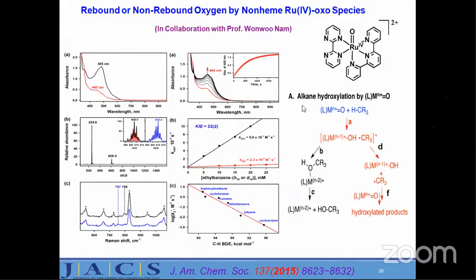So what is a rebound mechanism? If you look at this particular mechanism here, you have a metal oxygen species. The hydrogen is abstracted, and it remains here. You have a radical, and then you have OH. Once hydrogen is abstracted, the hydrogen goes with the oxygen, so it becomes manganese plus 3, and then this becomes a radical.